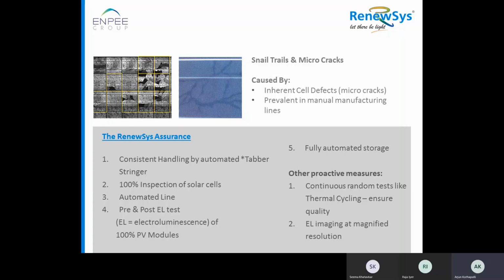Other proactive measures: we conduct random thermal cycling to ensure quality. Thermal cycling is where the temperature changes from -45 degrees to +85 degrees in a span of 5 hours. The different components in the module have different temperature coefficients. We simulate that in chambers. It's nothing but day and night. In the morning we have lower temperatures, during the day temperatures go high, and during the night it comes down. The same thing we simulate in our chambers to see the effect on the module. And we do EL imaging again.